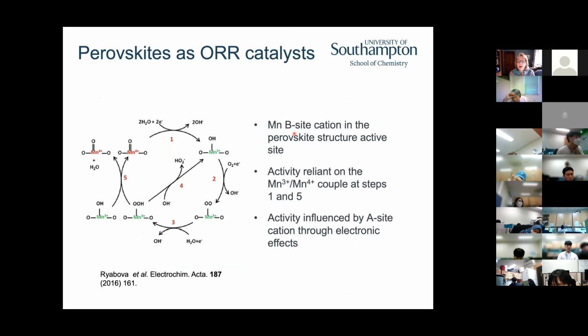So finally, I want to talk very briefly about some perovskites as oxygen reduction catalysts. And here we're going to look at the manganates, right? There's been a lot of work that looked at how the manganese B site cation is the active site, and it's been proposed that the activity is reliant upon the turnover between this manganese 3 and manganese 4 couple, right? So you need to be able to keep accessing this whole loop if you want to get the full 4 electron reduction of oxygen to make water, as opposed to being trapped here in the 2 electron reduction, where you're going to make the peroxide species.